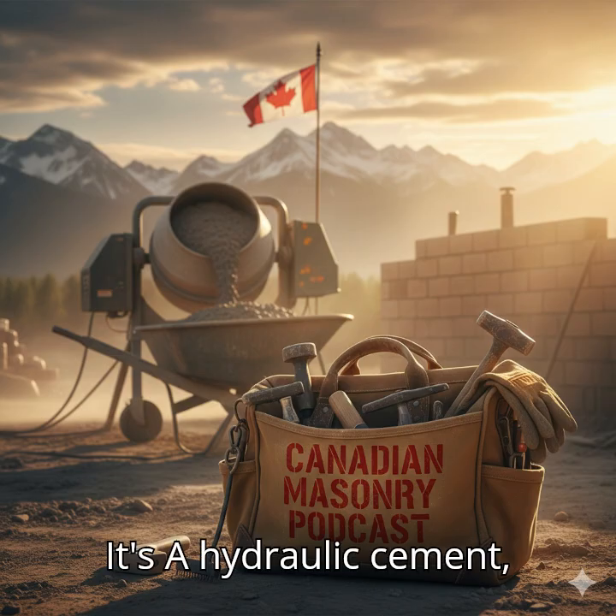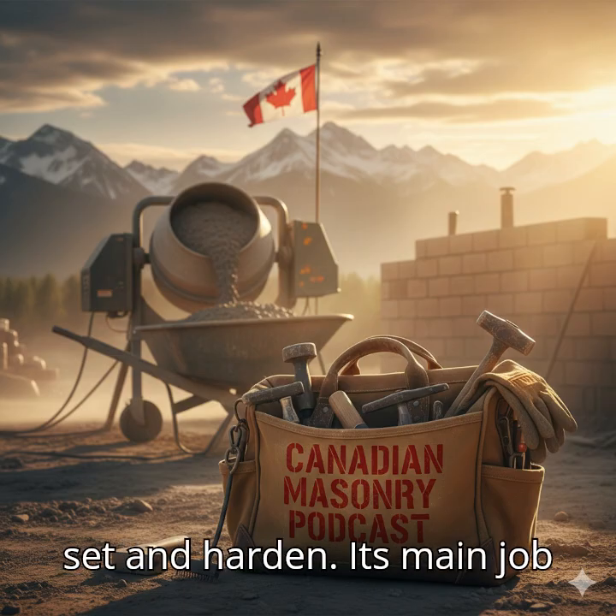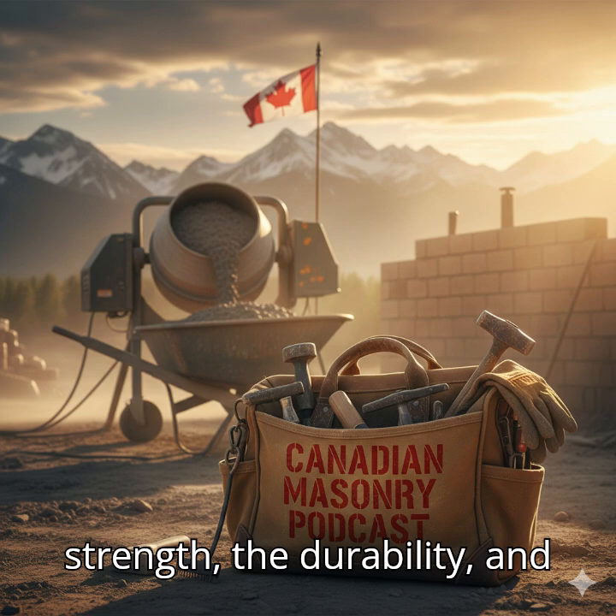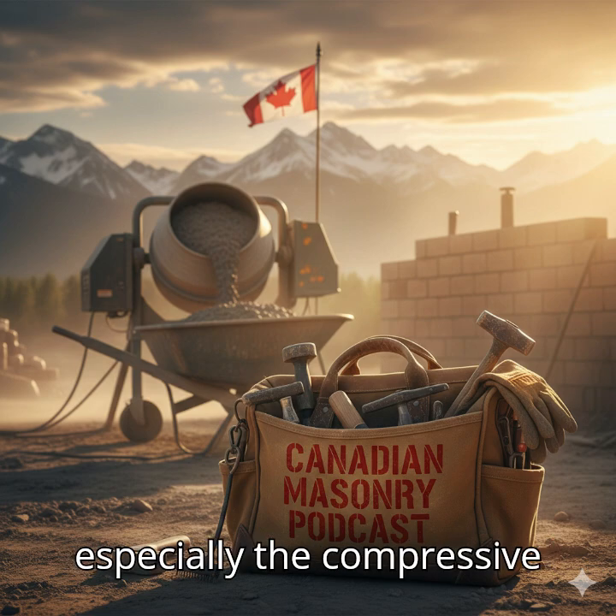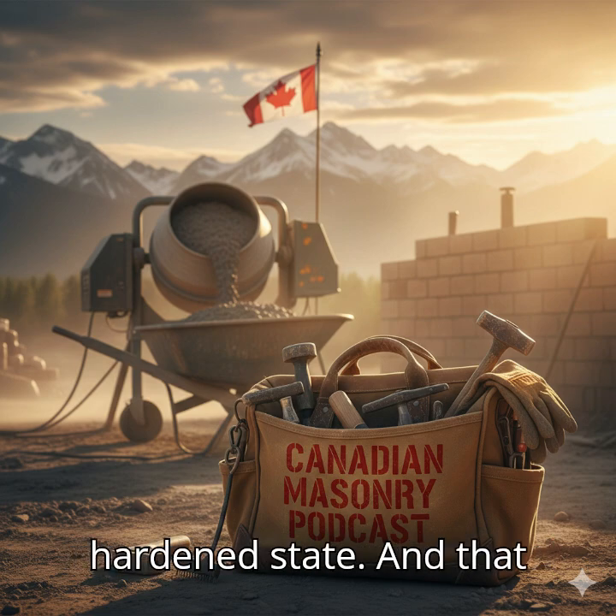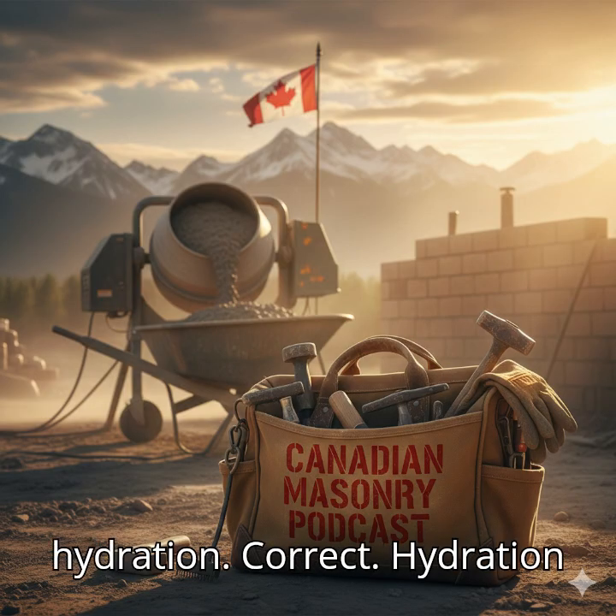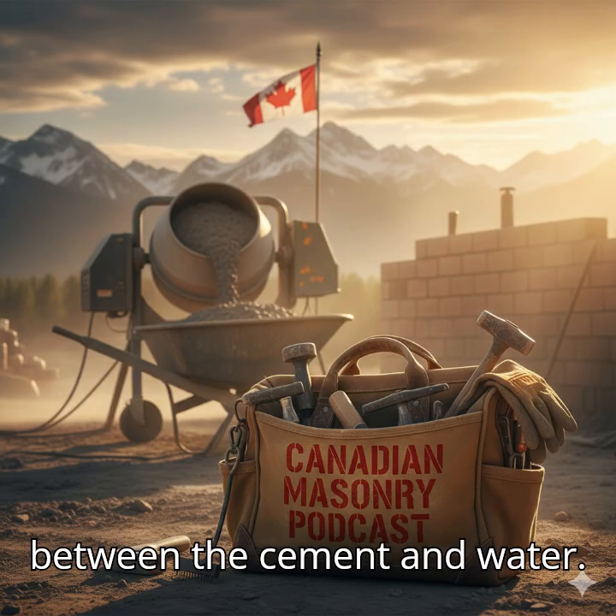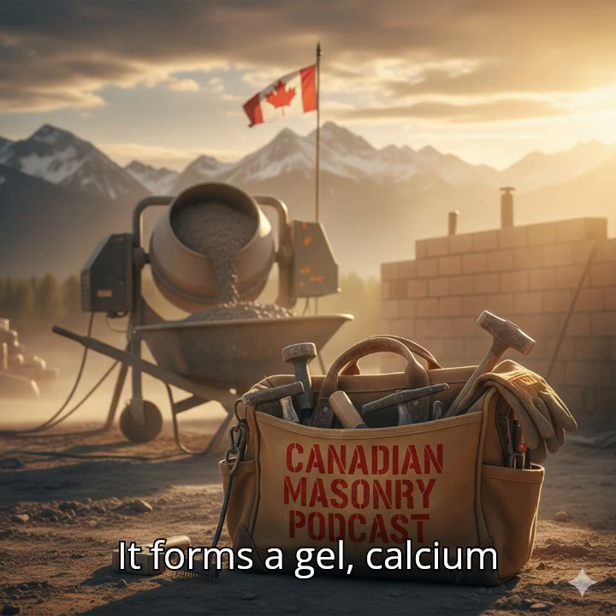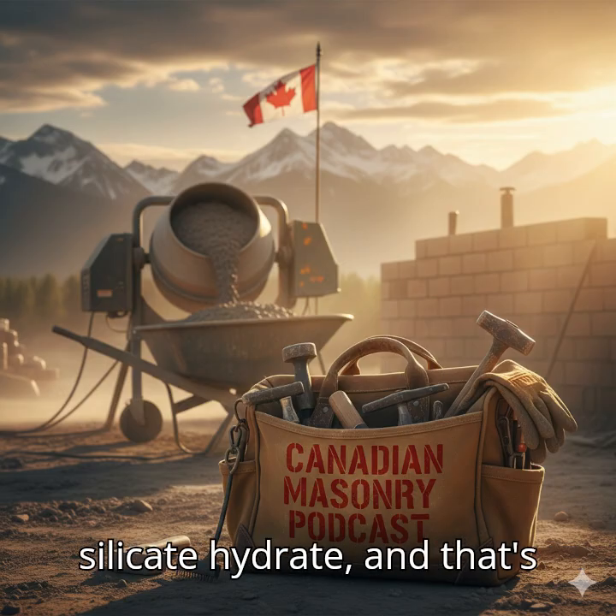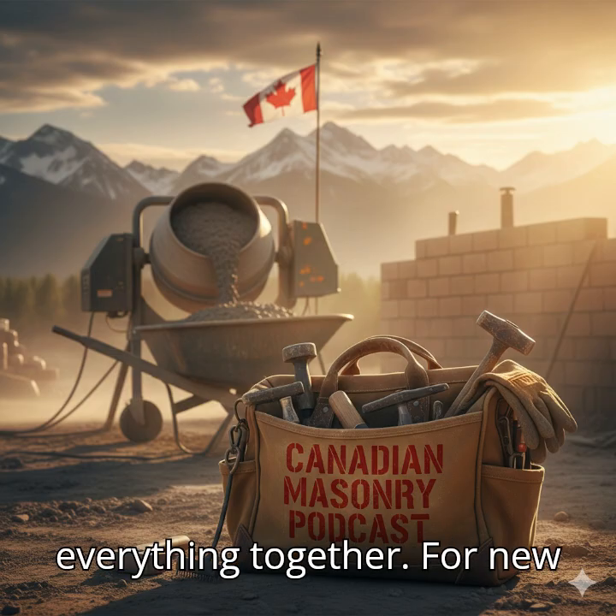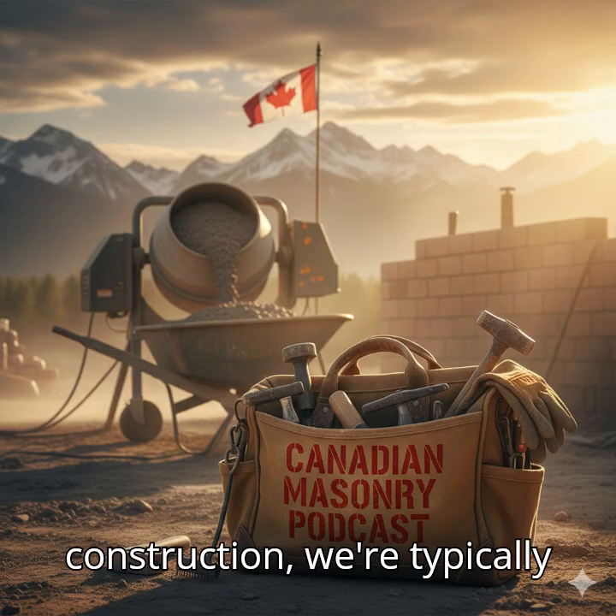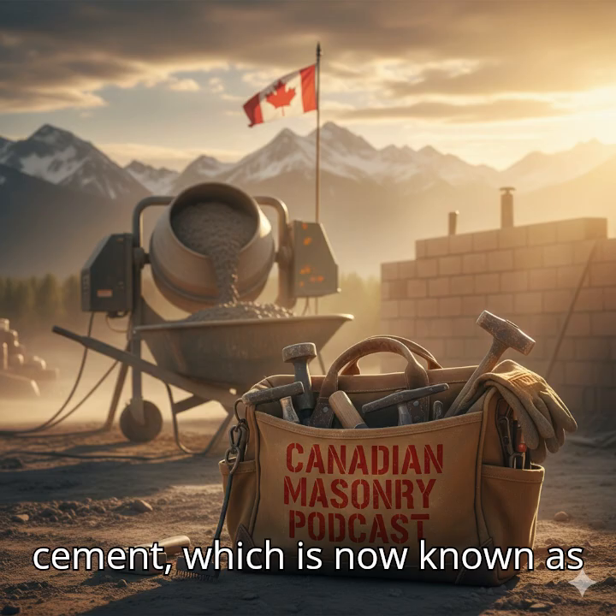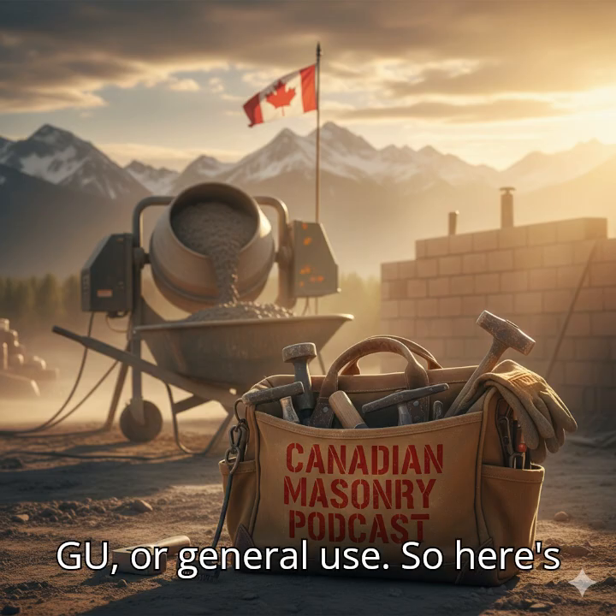It's a hydraulic cement, which means it needs water to set and harden. Its main job is to drive the bond strength, the durability, and especially the compressive strength in that final hardened state. And that setting process is called hydration. Correct. Hydration is the chemical reaction between the cement and water. It forms a gel, calcium silicate hydrate, and that's the glue that binds everything together. For new construction, we're typically using Type 10 Portland cement, which is now known as GU, or general use.